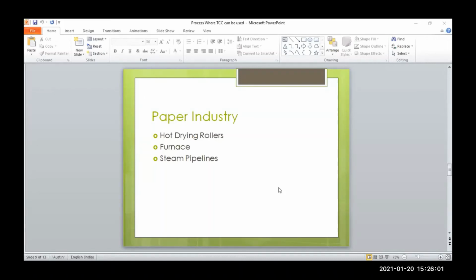We have a very special product for steam pipelines called thermoceramic coating steam pipe insulation, TCC SPI. This coating is very special, and it can be a substitute for glass wool. For example, if you are using around 75 mm of glass wool thickness on this steam pipeline, that can be reduced to 25 mm by our coatings. Glass wool insulation only takes care of conduction heat losses, but our coatings are very helpful to reduce radiation, conduction and convection heat losses. The typical ROI comes down to 2 to 3 months only. So it's a very revolutionary product for steam pipelines.